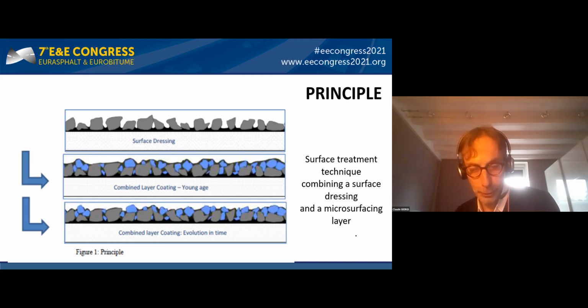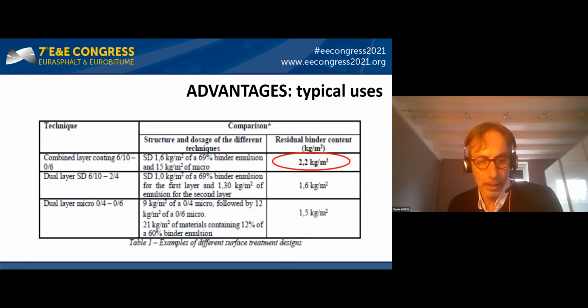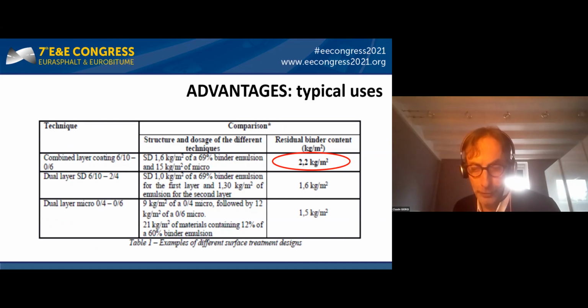Indeed, the initial microtexture of the microsurfacing layer can be relayed after wear of it by the emerging microtexture of the gravel head of the surface dressing layer. The advantage of this technique compared to traditional surface treatment is given by this table. The residual binder content of a combined layer pavement compared to either a dual layer surface dressing or dual layer microsurfacing is higher. This high surface rate of binder partly explains the great interest of this technique for waterproofing on crack support.